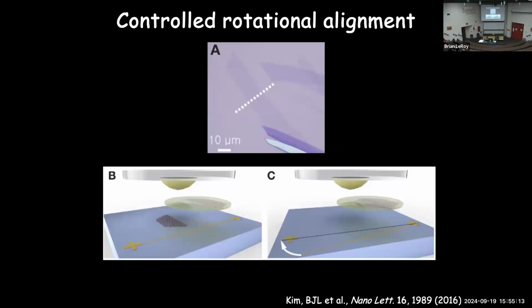So in this graphene on graphene, if you want to make this heterostructure where you control the twist angle, it's very important that you are able to very well define the twist angles between them and accurately control them, because the electronic properties are actually going to be quite sensitive to that twist angle. And so we developed a technique to actually do this with a very controlled rotational alignment between the two layers. And so what you see here, this is a monolayer of graphene up here, and we tear it in half. So we cut it in half at this point here where the white dashed line is. That way we know that the two pieces of the graphene are exactly the same crystal alignment with each other.